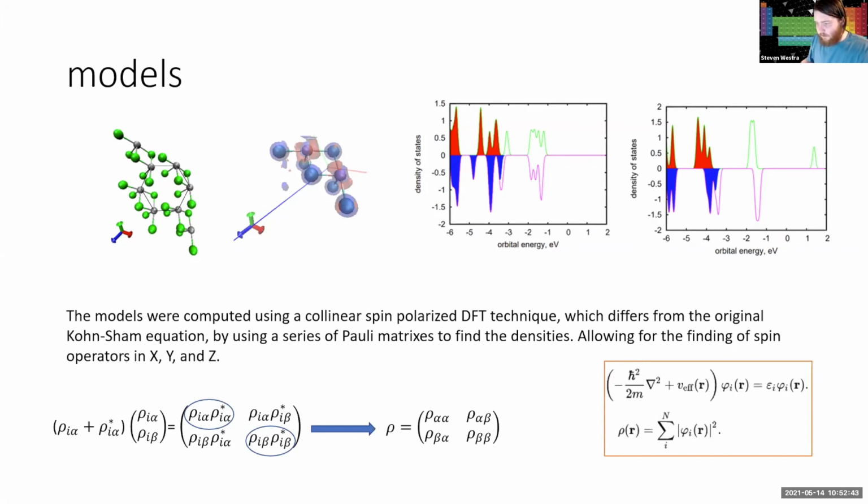And we have our density of states for two different spin conformations. Left is the antiferromagnetic, where we have all paired spins, one up, one down. And the right is the ferromagnetic, unpaired spins, where we have two up. It's not entirely obvious from looking at that, but it is found that the antiferromagnetic is the more stable of the two, with a slightly lower total energy.